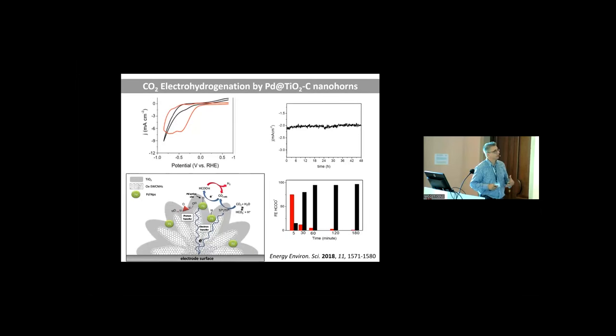The same strategy, but with a, let's say, more complex material, was used to investigate the CO2 to formate reaction. In this case, the work was inspired by a beautiful JACS paper of Cargnello from Stanford, showing that palladium on carbon, under specific conditions, was able to transform CO2 to formates. Formic acid is an important liquid carrier for hydrogen. And here we stabilize the palladium hydrides inside the inorganic matrix, preventing the sintering. And the process works nearly at equilibrium.